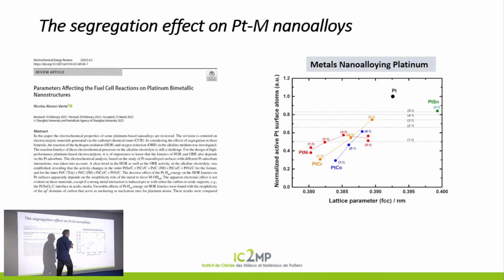And you observe that not all alloys here obey this position. What does it mean? Does it mean that the atoms at the surface are not really glad? They have to find an equilibrium, an energetic equilibrium, which is induced by the surface energy of the material. That is the reason. Now the question was whether nickel, chromium, cobalt, and all this stuff affect the hydrogen oxidation reaction in the same way as carbon. And the answer is yes.